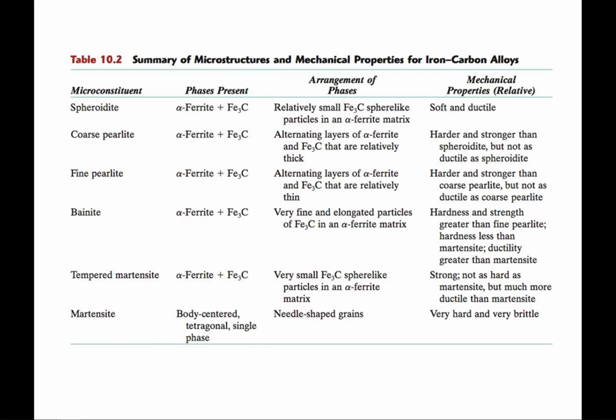All right, so let's get a summary then. This is finally all of the microconstituents or structures that we have for the steels that we're going to be concerned about in this course. And on this chart here, 10.2, they're listed in order from the weakest to the strongest, highest strength structure. And so spheroidite is again the weakest of them all, then followed by coarse pearlite, fine pearlite, bainite, tempered martensite, and then martensite. Okay. And then these are also listed in terms of decreasing ductility. So the spheroidite is very soft and ductile, all the way down to the martensite, which is very brittle. And then we just have a description of each of these structures.